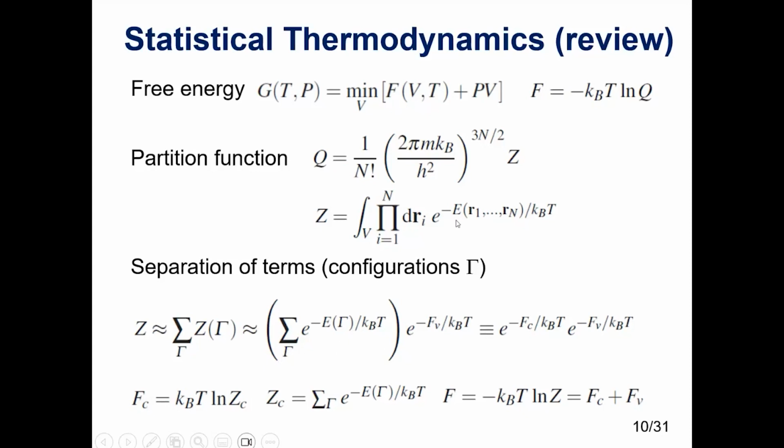Now, there is an energetically preferred set of positions for a given arrangement of chemical species. What this means is if you put the chemical species on a lattice, there might be small forces due to the random environments. And so we then want to relax those forces. And so every arrangement of chemical species has an optimal relaxed energy. That's what I call E of gamma.